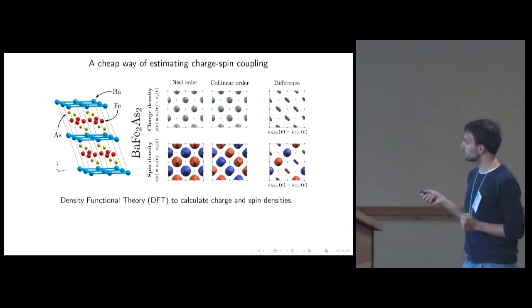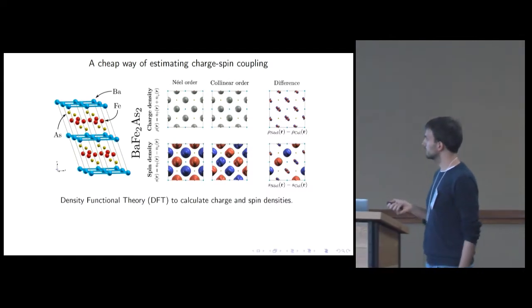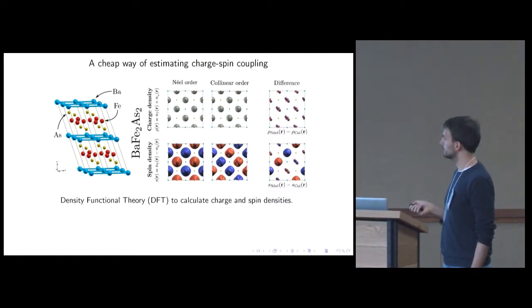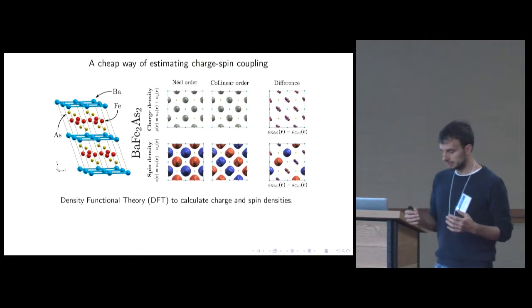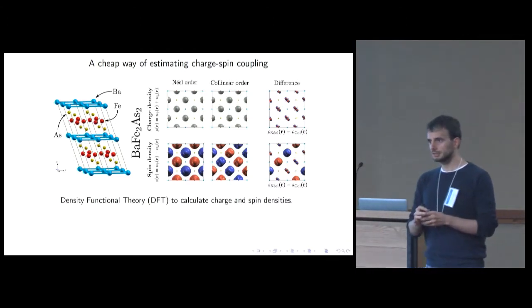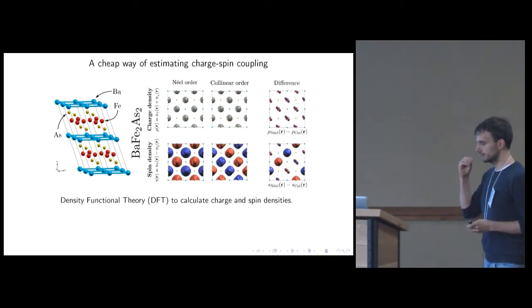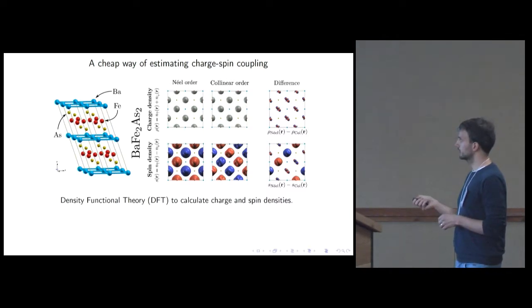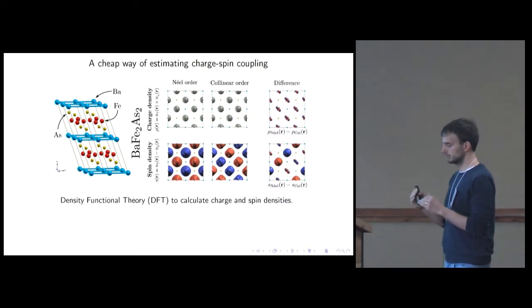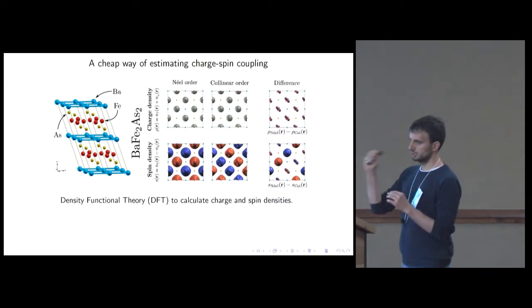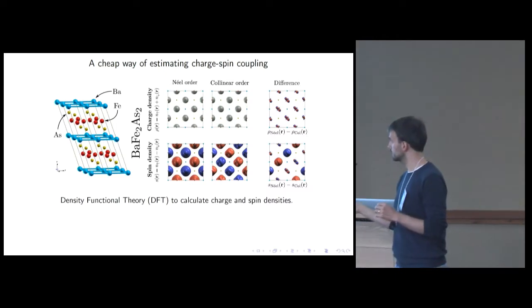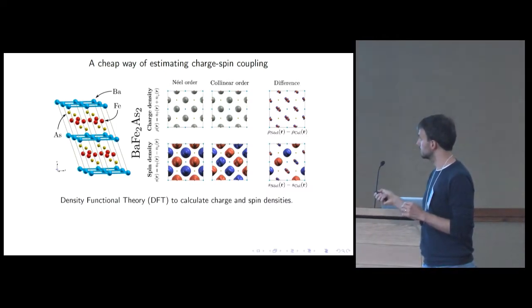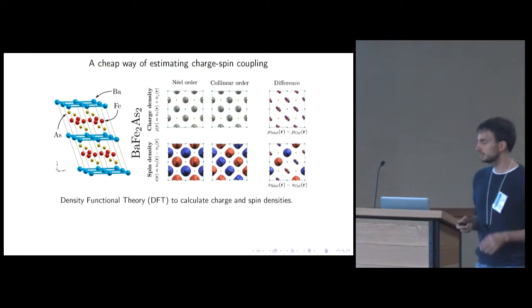Red and blue stand for positive and negative. We do the same thing for the spin densities. And then we essentially construct a kind of susceptibility, where we are taking the ratio of these two and seeing, okay, we change the magnetic order from here to here. How does charge density rearrange in that case?